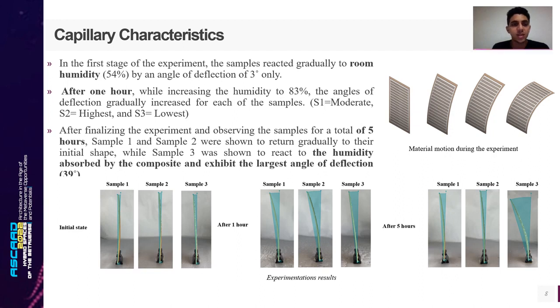After finalizing the experiment and observing the samples for a total of 5 hours, samples 1 and 2 were shown to return gradually to their initial shape, while sample 3 was shown to react to the humidity absorption by the composite and exhibit the largest angle of deflection, which was 39 degrees.